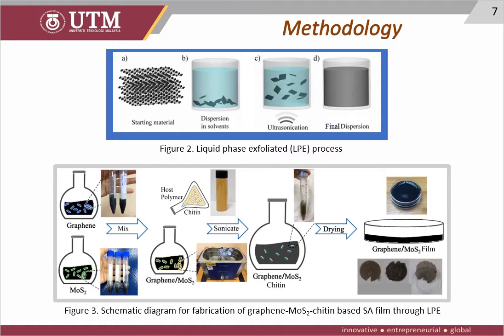Okay. For methodology, Graphene-MoS2 is prepared through the liquid phase exfoliation, LPE, process, as shown in this figure 2. The starting material is normally in the form of bulk crystal. We disperse it in suitable solvents for ultrasonication. The sonication process allows exfoliation of bulk crystals into nanosheets, and the process involves the weakening of van der Waals interaction inside the material due to the production of microjets and shock waves from collapsing cavitation bubbles. And figure 3 shows the schematic diagram for fabrication of Graphene-MoS2 chitin based SA film through the LPE.